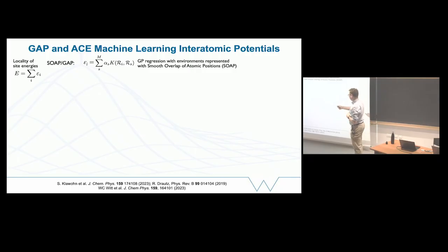And this kernel here compares the environment in which we'd like to make a prediction, EI, that's the energy we'd like to predict, this is its environment, with a set of representative configurations, RS. Then there's a coefficient that we learn when we fit the model that tells us how much each representative environment contributes to predicting the energy. So you can view it as Gaussian process regression, if you're familiar with that, or kernel ridge regression. We have a kernel in here, which is where all the nonlinearity goes, but these alphas are actually just a linear model.